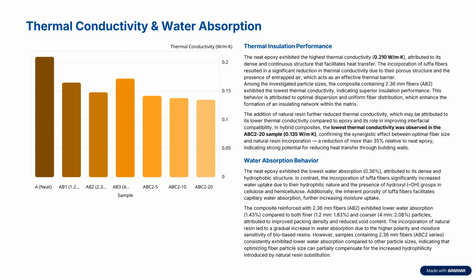The neat epoxy exhibits the highest thermal conductivity, attributed to its dense and continuous structure that facilitates heat transfer. The incorporation of Luffa fibers resulted in a significant reduction in thermal conductivity due to the porous structure and the presence of entrapped air, which acts as an effective thermal barrier. However, the addition of natural resin further reduced the thermal conductivity, which may be attributed to its lower thermal conductivity compared to epoxy and its role in improving interfacial compatibility. In hybrid composites, the lowest thermal conductivity was observed in the ABC2-20 sample, confirming the synergistic effect between optimal fiber size and natural resin incorporation.